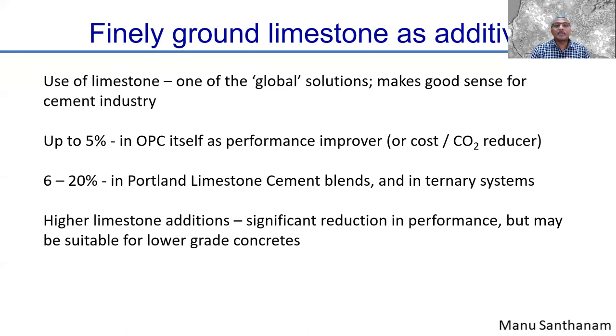Now, sometimes it pays dividends to actually start using limestone in the ground form along with supplementary cementing materials in so-called ternary systems. Ternary means we have more than two types of binding materials available. Of course, cement is one of them. Second here is limestone. And the third is a supplementary material like fly ash or slag, or calcined clay, because we want to maximize the reactivity of the SCM. So limestone and calcined clay as a popular combination has come across as a very important substitute for cement in the last few years.